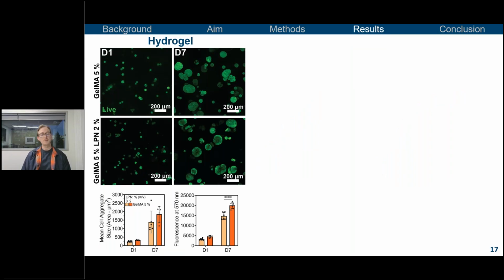Next, we did some biocompatibility studies, starting off in hydrogel constructs using GelMA 5% with and without Laponite at 2%, with the MCF7 breast cancer cell line. What we were able to see over the course of 7 days was that in both the controls and Laponite, it was capable of forming these spheroid structures, which were also metabolically active and increased in size over time.